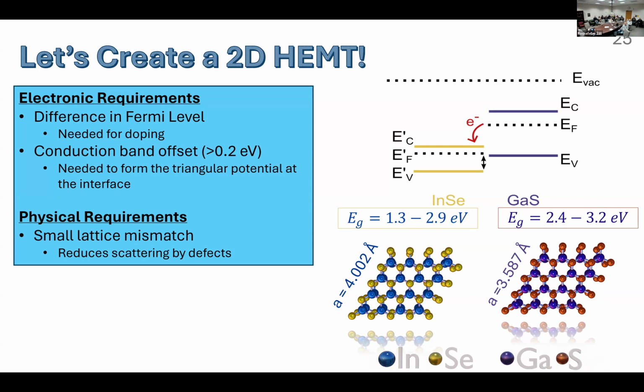If we look at the band or electronic properties of indium selenide and gallium sulfide as presented on the right, we see that they do have a difference in the Fermi level, meaning that we can, in theory, dope the indium selenide by placing the gallium sulfide on top. Additionally, they do possess a conduction band offset. So in theory, there should be the formation of a triangular potential at the interface. Finally, even though they don't have exactly similar lattice constants, they do have a similar lattice structure. And so ideally, we will see whether or not that plays a role in whether or not we can make these 2D HEMTs.